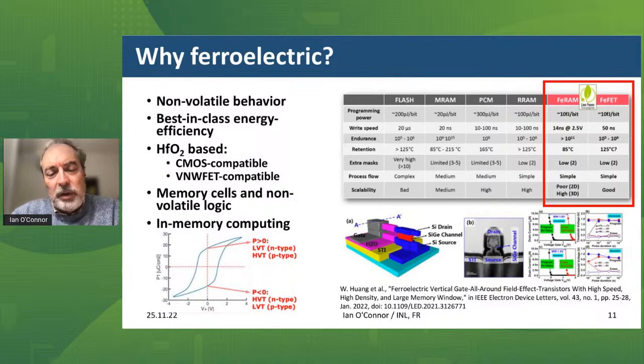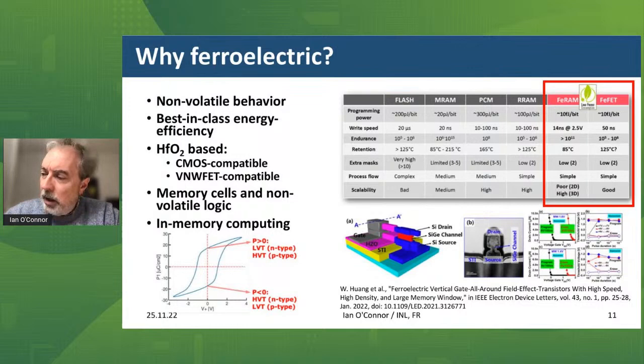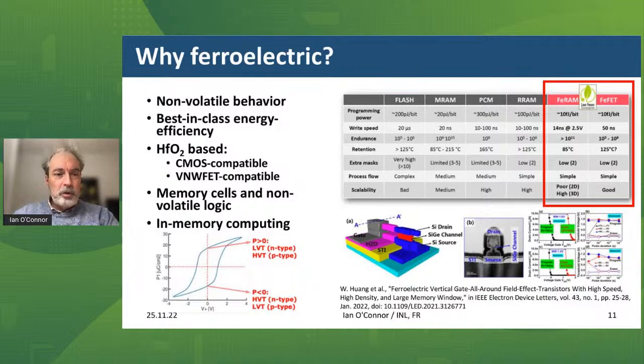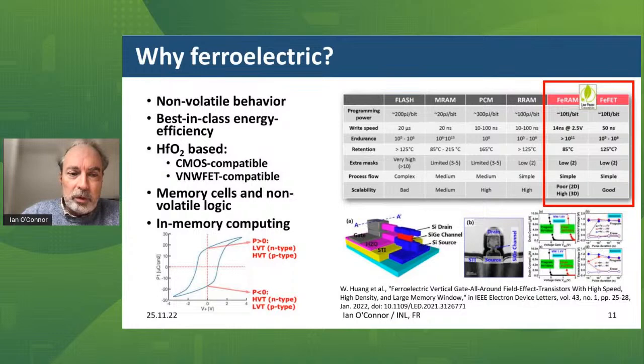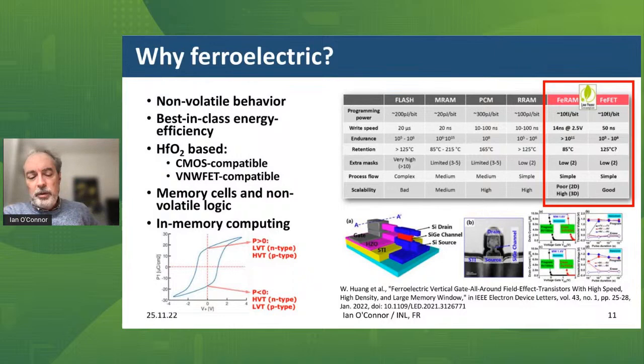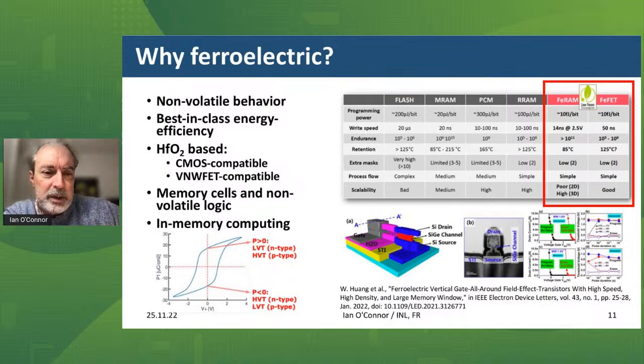It's based on hafnium oxide — a key observation leading to CMOS-compatible ferroelectric. In 2011, a discovery was made that hafnium oxide can be made ferroelectric. Hafnium oxide is fantastic because we already use it in CMOS processing, making it inherently CMOS-compatible. It's also been proved compatible with vertical nanowire FETs, as published earlier this year on ferroelectric vertical nanowire FETs. You can use this to build non-volatile memory cells, but also to do what we call non-volatile logic — shifting the threshold voltage is key to getting different functionalities inside logic cells.